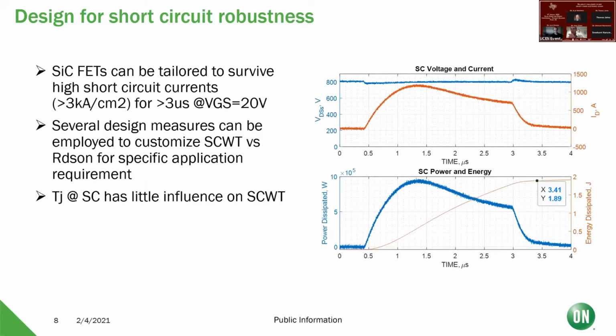Next one. I think this is the final picture here. Let me just double check. Two more things to mention. One here on short circuit robustness, and no matter what kind of applications, there are conditions where the device finds itself, at least in a transient period, in short circuit. It needs to withstand that for a period of time, 1.5, 2, 3 microseconds. And silicon carbide is considerably more robust than the silicon counterparts. So we're going through these characterizations, which tend to be very application specific. And so it's one thing to specify this for a device generically, but typically you need to identify also what the circuit conditions around that are.